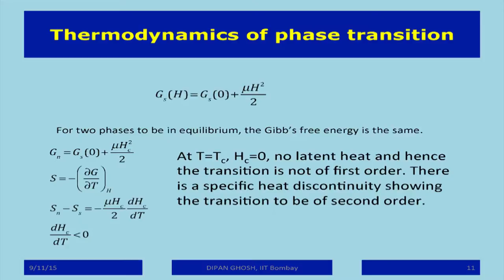I can calculate the entropy by differentiating the Gibbs free energy. These are basic thermodynamics. And what we find is there is a difference between the entropy of the normal state and the superconducting state. That quantity, Sn minus Ss, happens to be this, it is just a differentiation of this quantity. So since it is found that the critical field varies with temperature in such a way that dHc by dT is always negative, we make a statement that the superconducting state has a smaller entropy than a normal state. As you know, entropy is a measure of the order, so therefore the superconducting state is more ordered than a normal state.